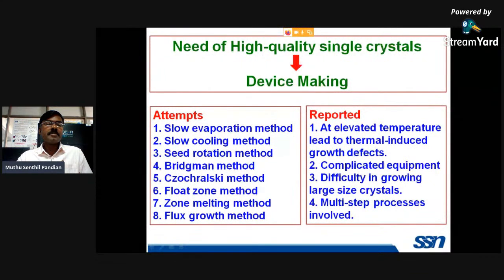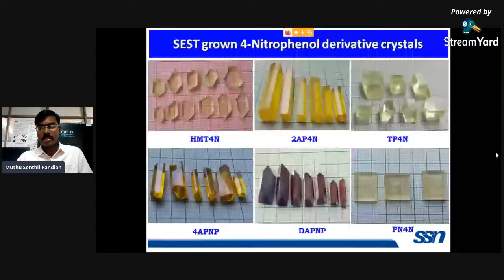Several attempts have been made to grow the crystals by using the slow evaporation method, slow cooling method, and seed rotation technique. Melt growth techniques like the Bridgman method, Czochralski, float zone, zone melting, and flux growth method. But all the reported methods are at elevated temperature, which leads to thermally induced growth defects, complicated equipment, and a difficulty in growing large size single crystals by solution method, and a multi-step process is also involved.